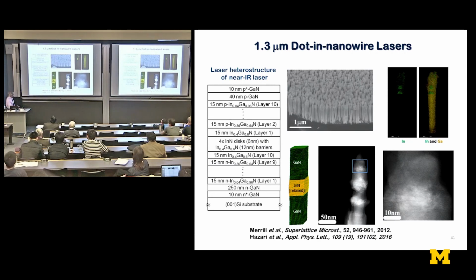And so here's some collaboration with Joanna. And she showed that these nanowire regions, they are cylindrical dots with an indium-rich core surrounded by a slightly gallium-rich shell. But nonetheless, they were quantum dots that were forming. And you see this blowout, and that was predicted by theory. It has to do with the atom kinetics on the growing surface.